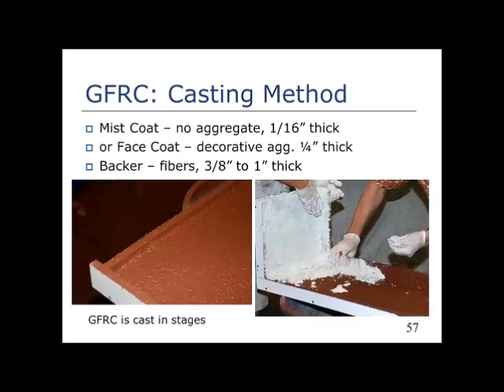And that mist coat is always sprayed in, because that's really the only way you can put it down so thin. Typically it's sprayed in about a 1/16 of an inch thick, no more than 1/8. But typically it's the 1/16 of an inch. It's basically like you're painting the inside of the mold.